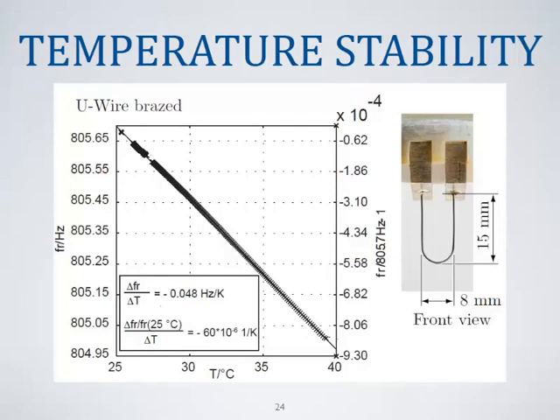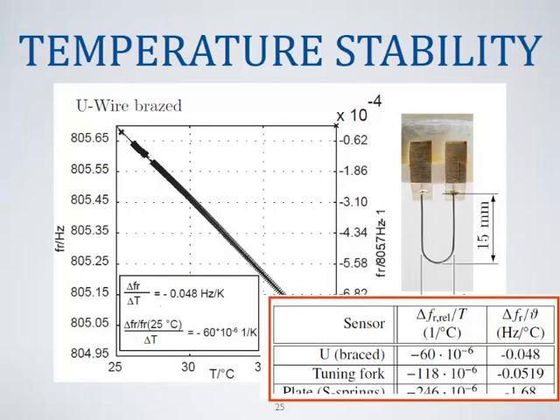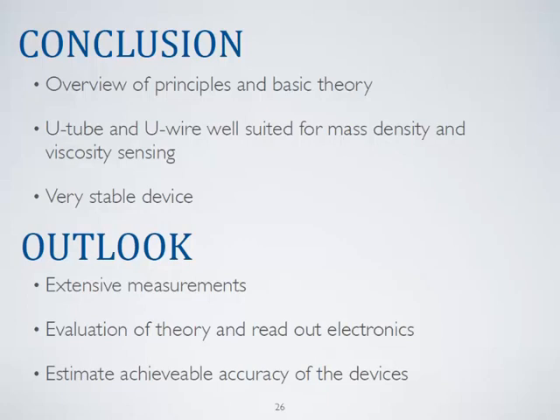We also did some measurements over temperature. What you see here are the evaluated resonance frequencies over temperature for the U wire. As you can see, the dependency to temperature is pretty weak. We tried to do these measurements for all of our sensors. It's not finished yet. Just to have any comparison, we went to a music store and bought a conventional tuning fork. The absolute deviation is almost the same. The relative deviation is even better for the U-shaped wire than for the tuning fork, which I think comes from the fact that stainless steel, which is used for tuning forks, has double the extension coefficient as tungsten, which we use for the U-shaped wire.